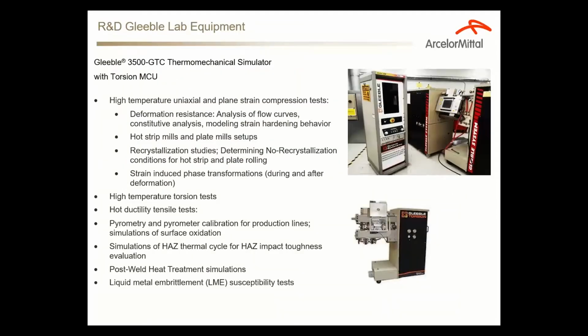Our Gleeble lab, as I mentioned, is a part of our research tool parks. We have a 3,500 machine with a torsion MCU, and quite recently we upgraded the control system to GTC, and it gave us a lot of new capabilities. What we're using this machine for is, of course, deformation resistance analysis of flow curves, constitutive analysis, strain hardening behavior, you name it. We use these results to help mills